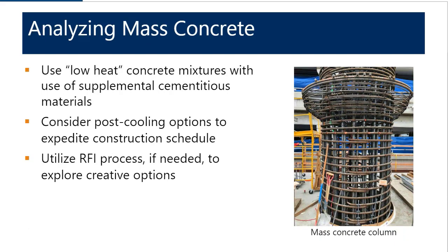So when you analyze mass concrete, some of the things to think about is beginning with the end in mind, Stephen Covey would say. And so you can use low heat concrete mixtures with the use of supplemental cementitious materials. So things like fly ash or gray, class F ash, even though it's difficult to get at this time period, is great for mass concrete elements. And you can use them in very high dosage. We've worked on projects where mass elements were using 40% class F ash and 50% class C ash.